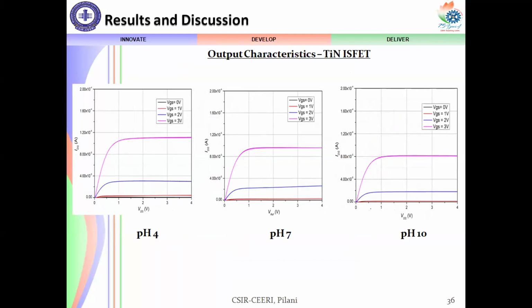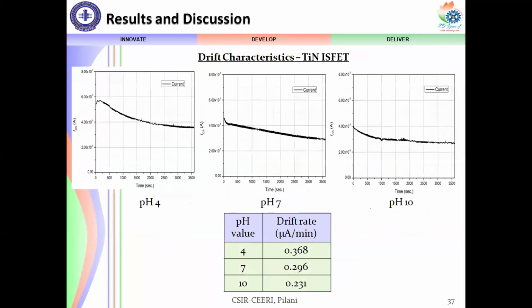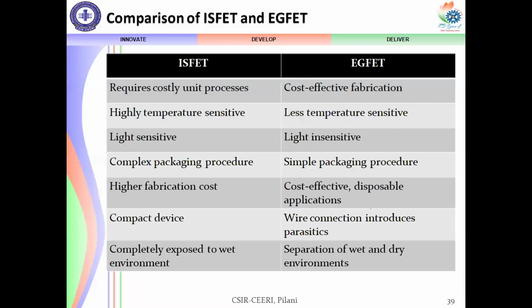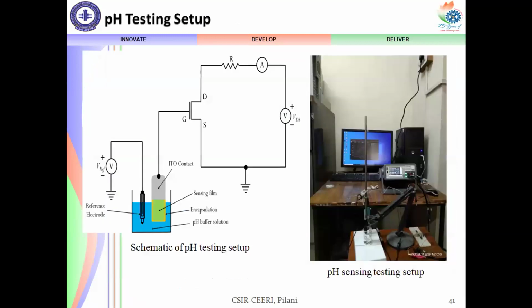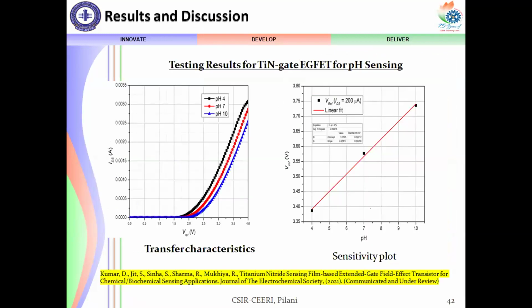We have tested at pH 4, 7, and 10 in a repeated way, and we have found that this film is very stable. So the development of titanium nitride is very successful. We have tested the drift analysis of TiN based ISFET also. Similarly, the extended gate field effect transistor was replicated by utilizing the same material. This is the pH sensing setup for those electrodes, and this is again the testing of EGFET utilizing a titanium nitride gate.